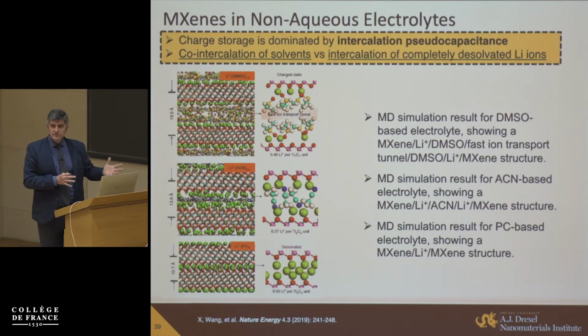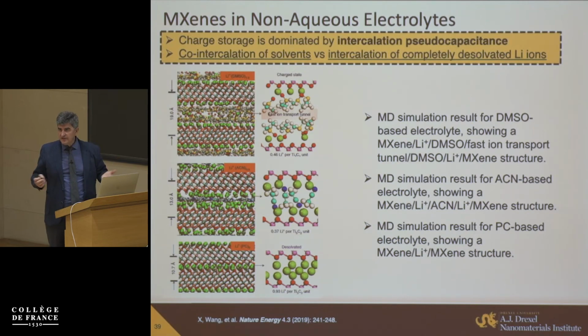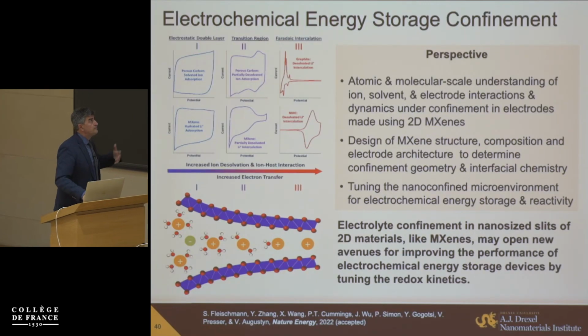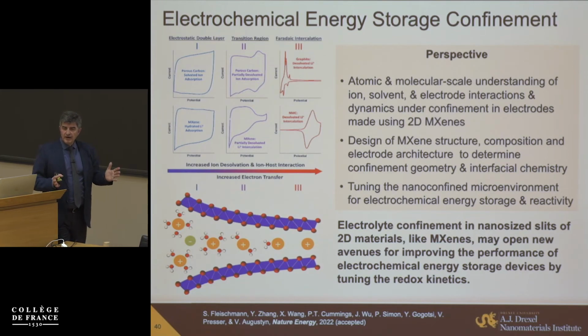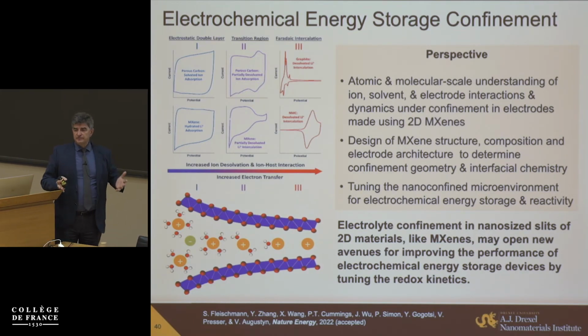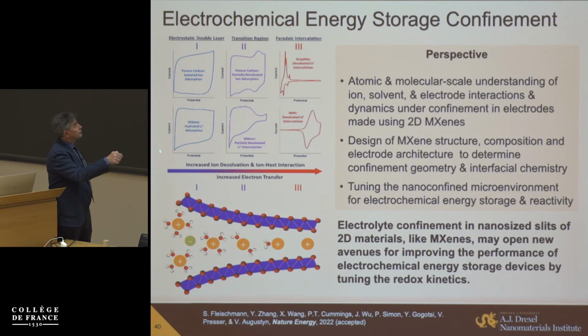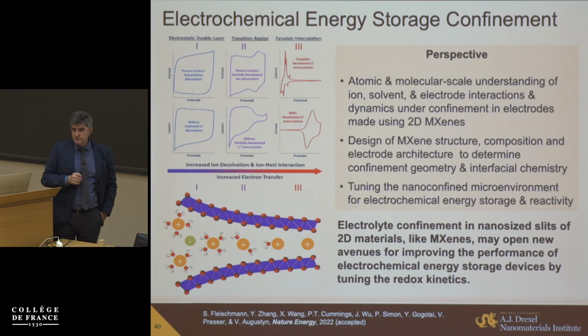So it just shows how different the behavior can be from what you may intuitively expect based on previous experiences or bulk predictions. What we are trying to do in our group is really to understand how, by confining electrolyte between layers of MXenes and other 2D materials in collaborations, we can control behavior, moving from double layer to this type of pseudocapacitive combination of double layer behavior and redox behavior, and eventually to purely battery-like redox behavior where there is much larger charge transfer from ions. You can express it as a degree of confinement.